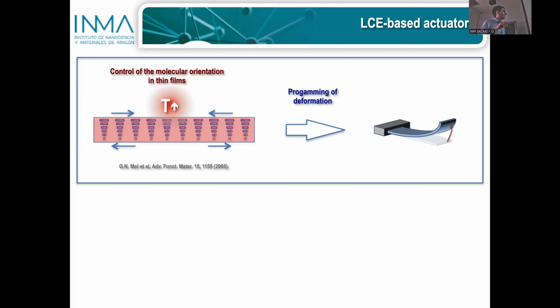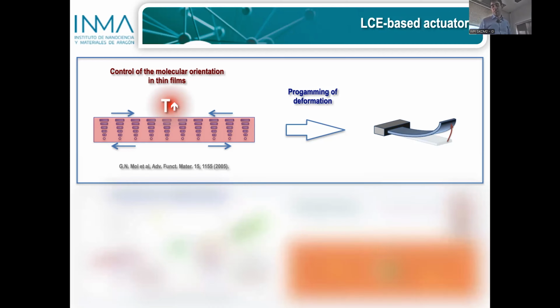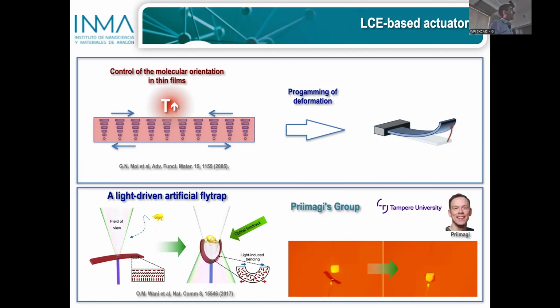And if you heat this type of film, following the deformation rule that we mentioned, this will generate a contraction in the top part of the film and an expansion in the bottom part of the film. And the system, in order to accommodate these stresses, has to bend up, as shown schematically here. And this has been used by our colleague at Tampere University, Harri Priimägi, to generate an artificial fly trap.